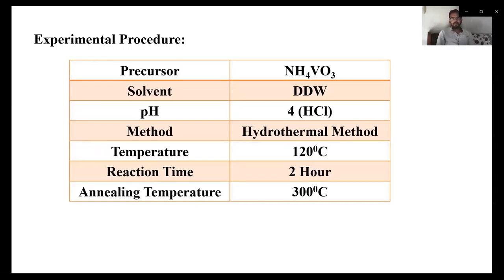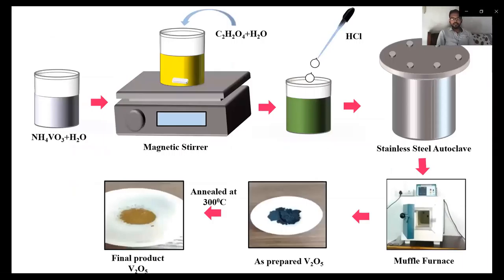We get a black blue colored solution with a black precipitate. This solution is filtered and annealed at 300 degrees Celsius. Finally, we get the yellow colored material, which is vanadium pentoxide. This is the whole process of synthesis of vanadium pentoxide.